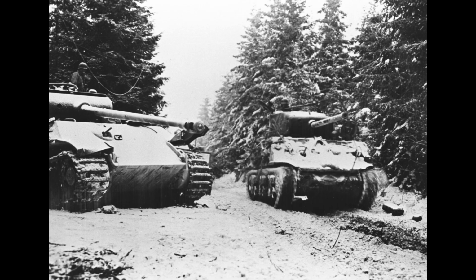Weld quality on late-war German tanks showed similar degradation. X-ray examination of welds on Panthers captured in early 1945 revealed porosity, incomplete fusion, and slag inclusions that would have failed quality inspection earlier in the war. These weld defects created stress concentrations that promoted crack propagation when armor was struck. Several examined Panthers showed cracks extending from impact sites along weld lines, indicating that poor welding had compromised armor integrity.